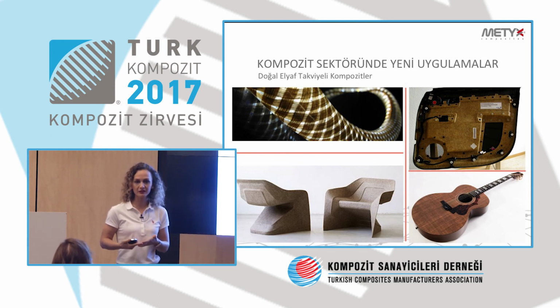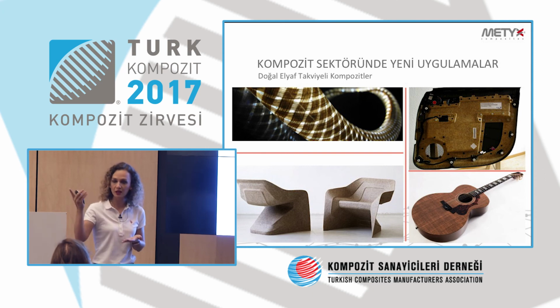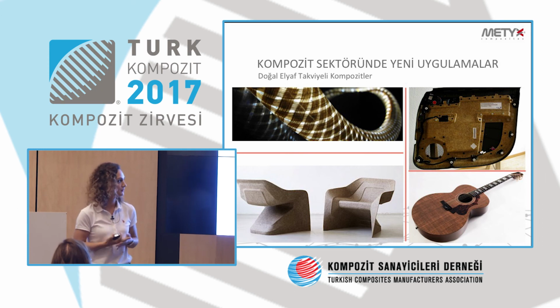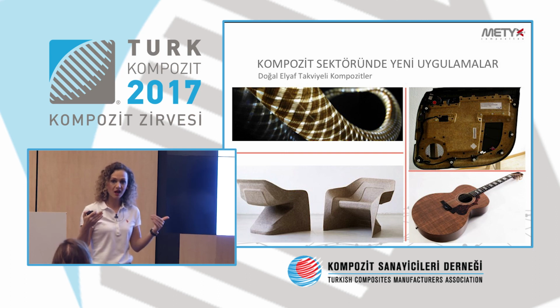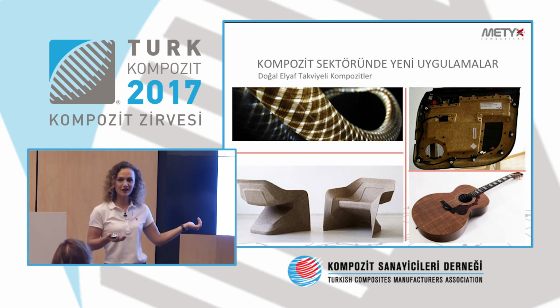The density is 1.4 grams per cubic centimeter. When we look at it, glass fiber is 2.6. When you produce a material, of course, this flax structure is lighter than the glass fiber. In the laboratory, we have created helmets, for example, and when you compare them with glass fiber, there is a huge difference in weight. And when you look at the resistance, it is almost the same, so you have a lighter product, but the performance is the same as the glass fiber.